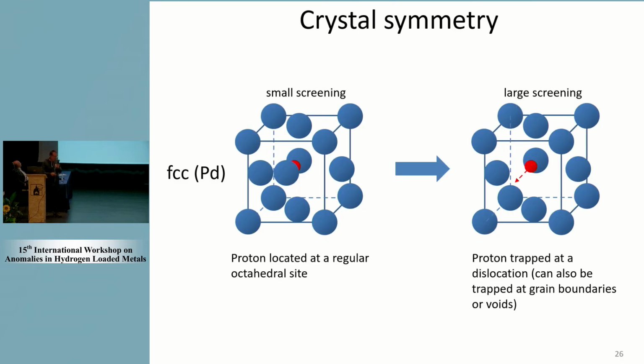So a little effort to try to explain this: this is the normal FCC lattice, and this red hydrogen sits at what we call an octahedral site in the middle of this cube. But when you remove one palladium from the lattice, this hydrogen is pulled away towards this vacancy. And there are more ways to try to do that, either radiation damage, or, as Natalia said, we tried in the past stretching the palladium.